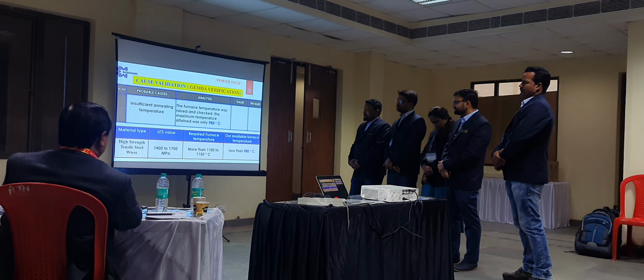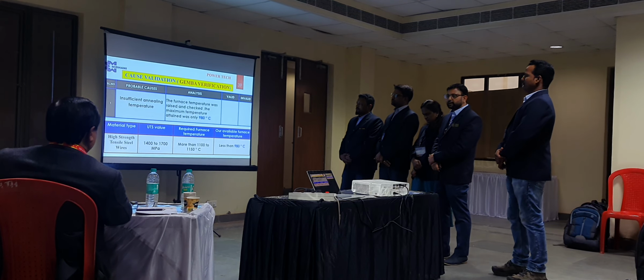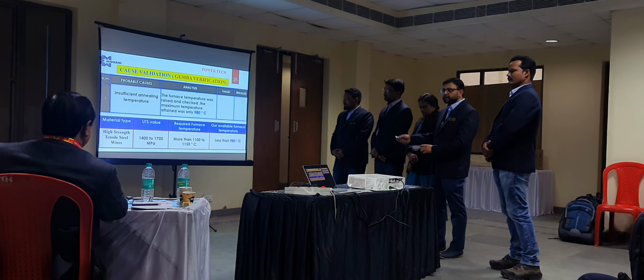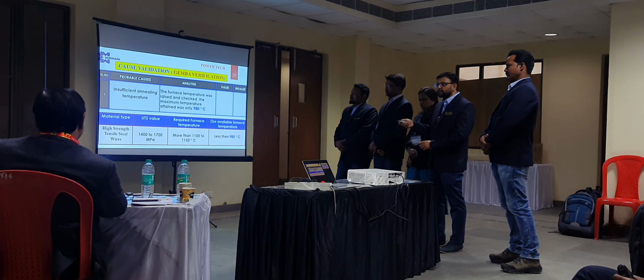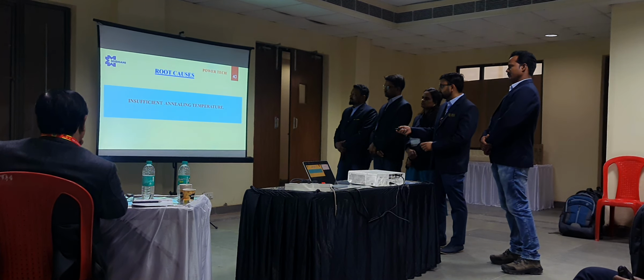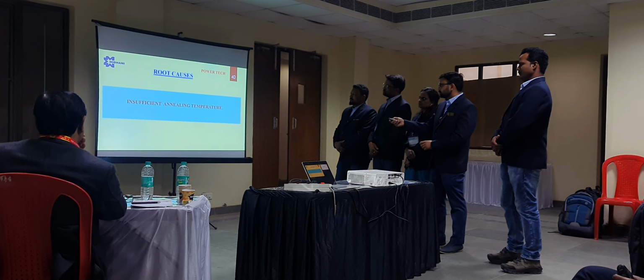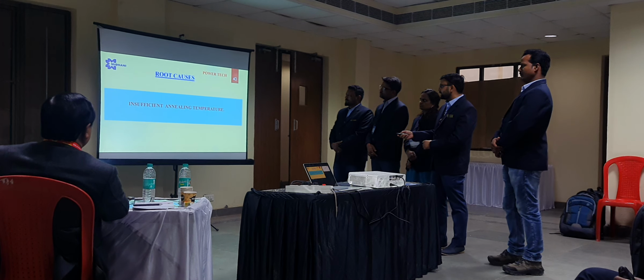After discussion with the Materials Department and R&D Department of MIDHANI, they suggested that for high-strength steel wire, the furnace temperature should be more than 1100 to 1150 degrees Celsius, whereas our available furnace temperature was only 980 degrees Celsius. So this was the possible cause for this problem, and we declared it valid. So the root cause of this problem is insufficient annealing temperature.